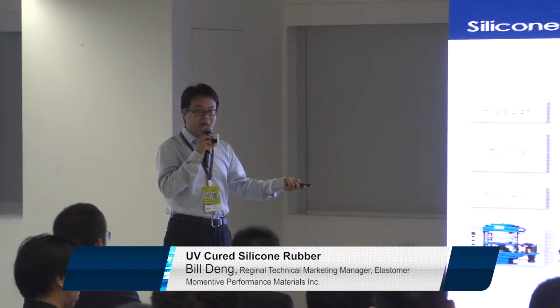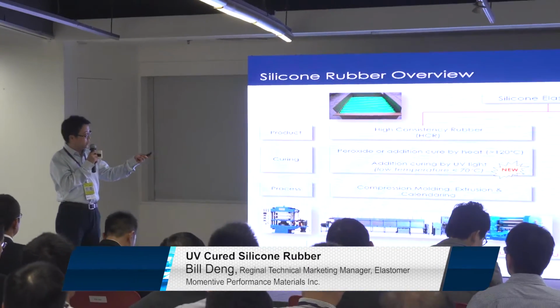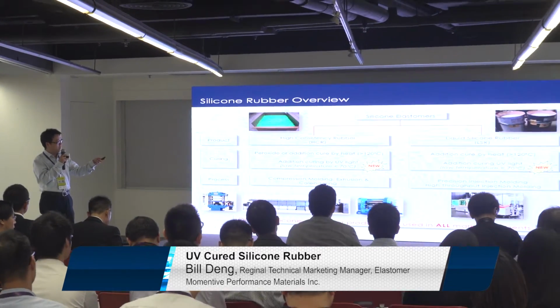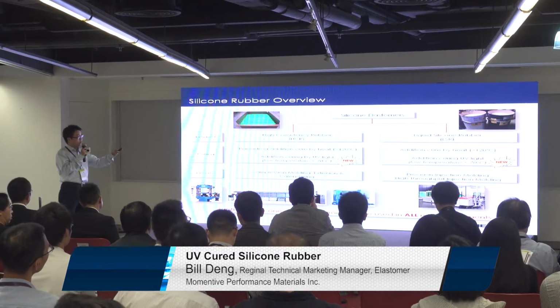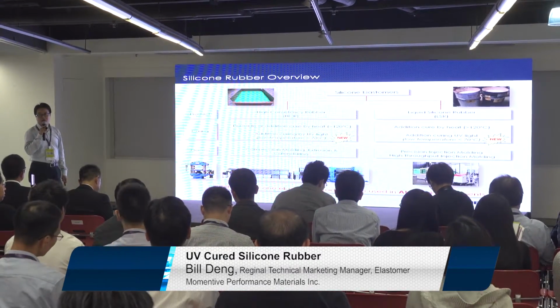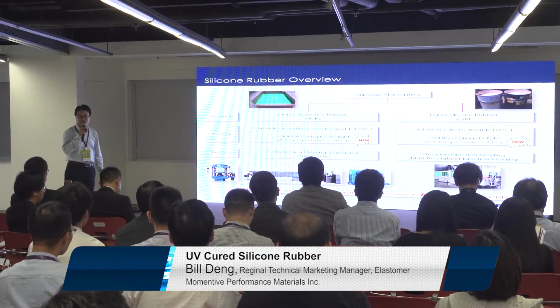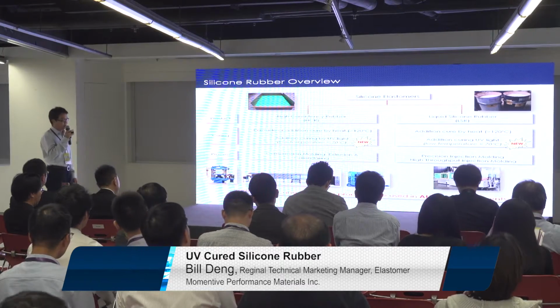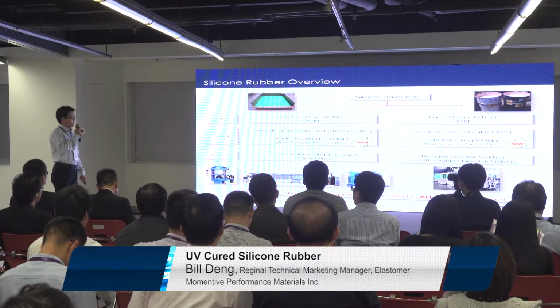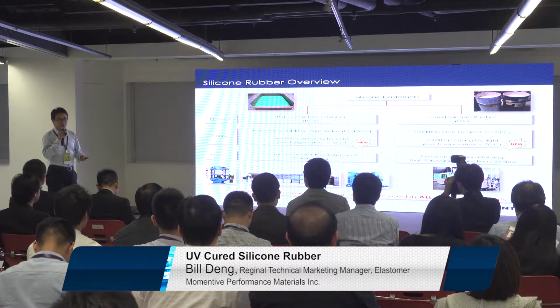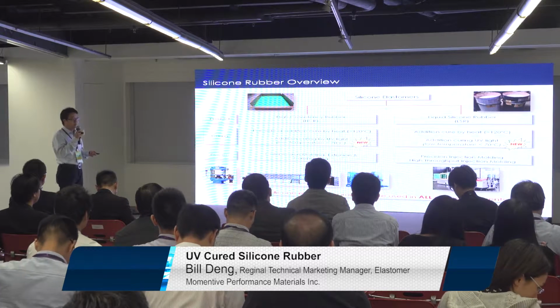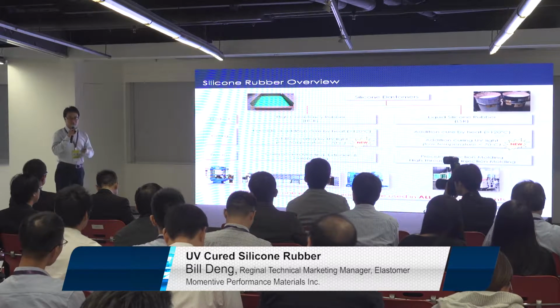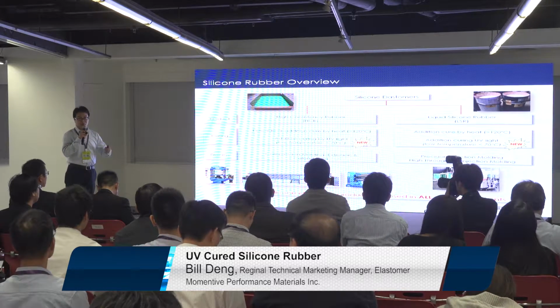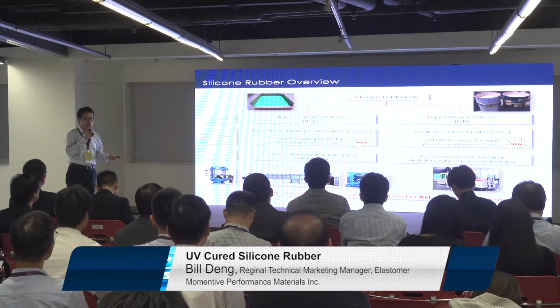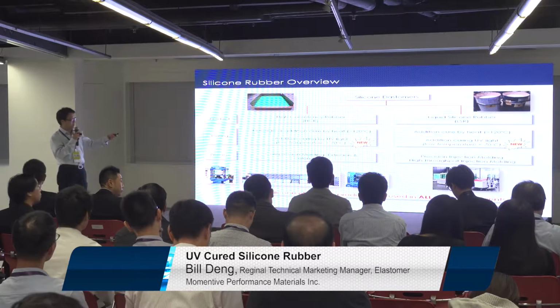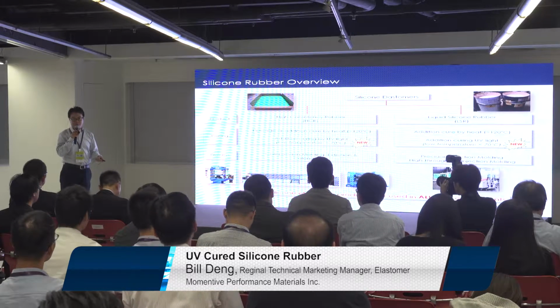In the following slides, I will use the abbreviation HCR for high consistency rubber, and LSR for liquid silicone rubber. Another one is the liquid silicone rubber. It is like a high viscosity slurry. The viscosity is usually between 200 pascal second and 500 pascal second, depending on different grades. Both of these rubbers are, for us as a material supplier, finished goods. But for the customer, both of them need a processing step, like compression molding or injection molding, to make the silicone rubber material into real rubber parts.